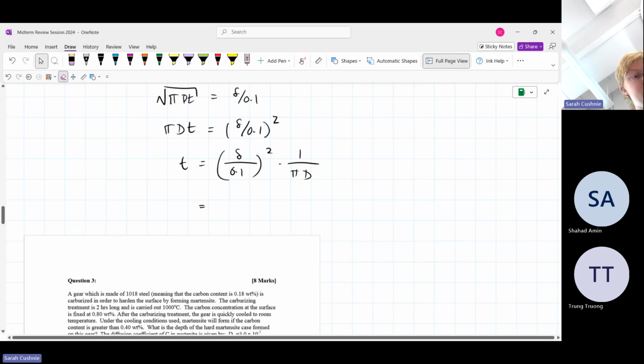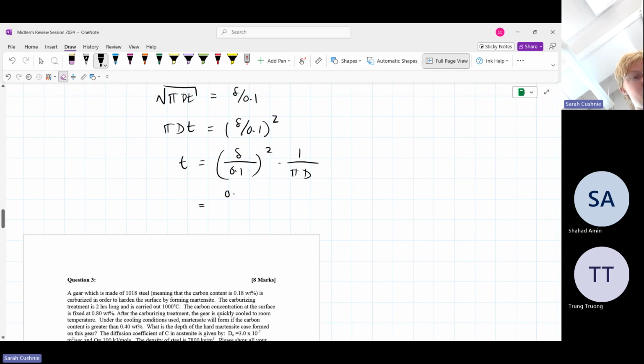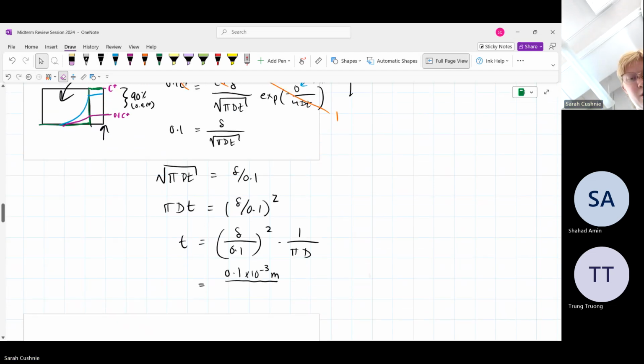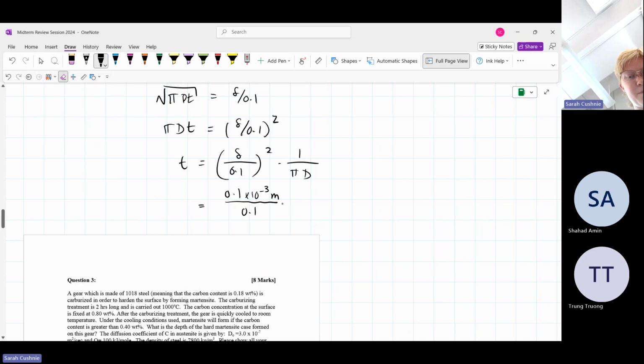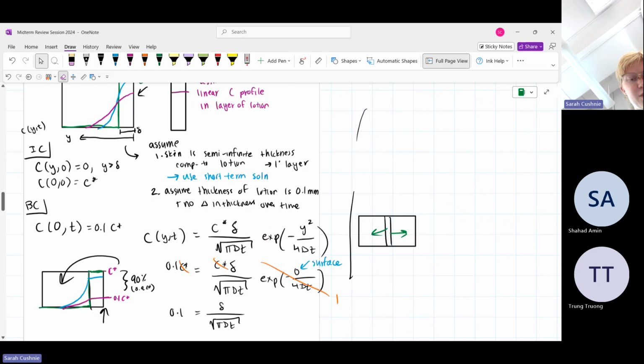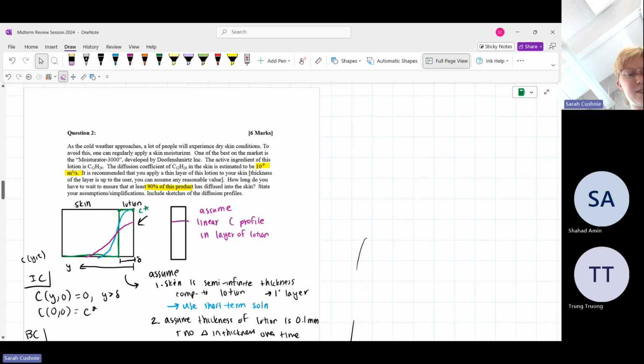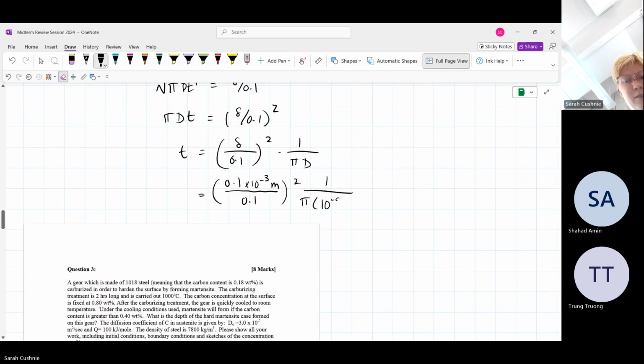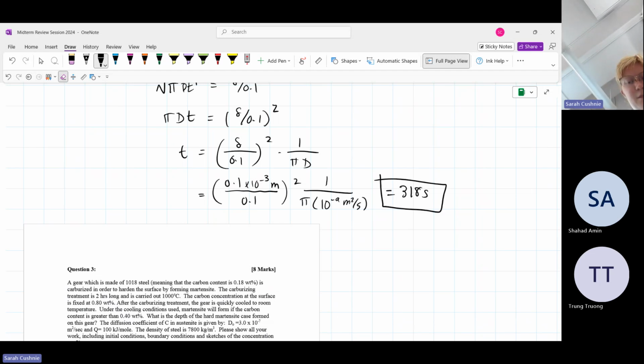So now we can sub in the values. Remember our delta was equal to 0.1 millimeters, so I'm going to convert that to SI units: 0.1 times 10 to the negative 3 meters, all over 0.1, squared, times 1 over pi, and then our diffusion coefficient, if you remember from the question, was 10 to the negative 9 meters squared per second. And if you calculate all this, I got a value of 318 seconds.